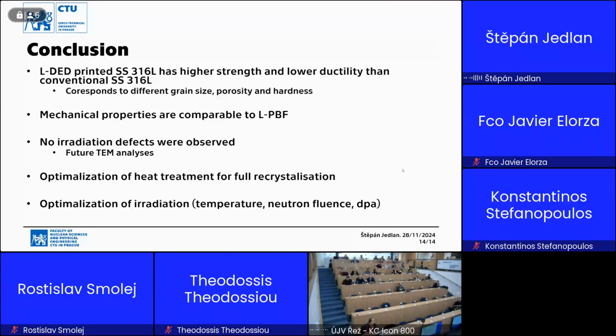Now, in the future, we would like to optimize the irradiation to obtain the same neutron fluence on each type of sample, and also we would like to address the heat treatment. And at the end, through the electron microscopy, namely the EBSD, we were not able to see any objects because the magnification is a little bit too low. So in the future, we would also like to do transmission electron microscopy to further address irradiation defects in the 3D printed material and compare it to the conventional one.